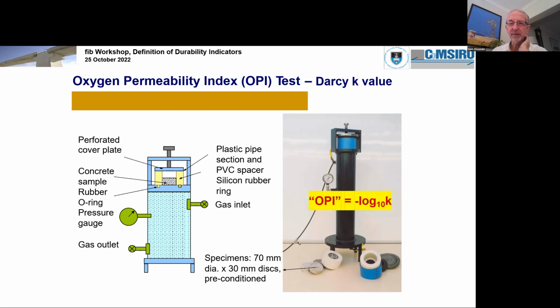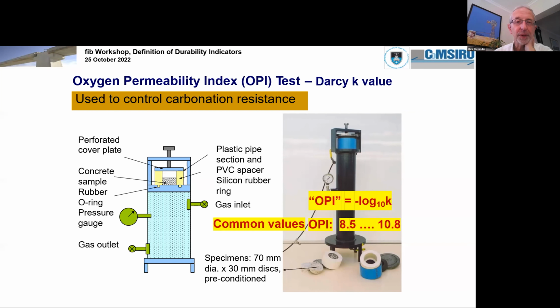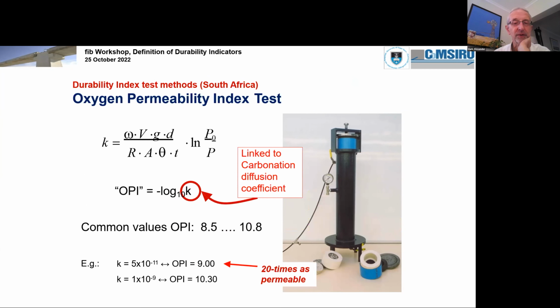So the OPI is defined as the negative log of the Darcy coefficient, just to make it into a more easily wieldable number. And the common values would be between about 8.5 and say 10 or 11, which on a log scale gives you nearly 3 orders of magnitude, which you would expect. And we use this to control carbonation resistance. And the Darcy equation is given there, and the K value, or the OPI value, which is the log of the K value, is linked to the carbonation diffusion coefficient. That allows us then, as you'll see in the model just now, to do some modeling of carbonation ingress.